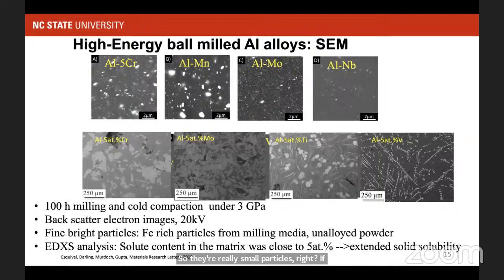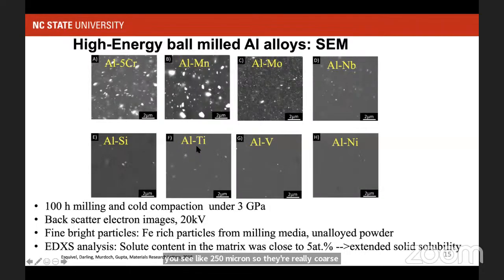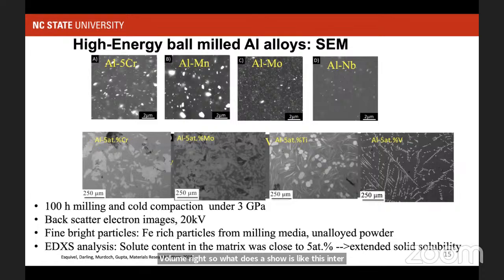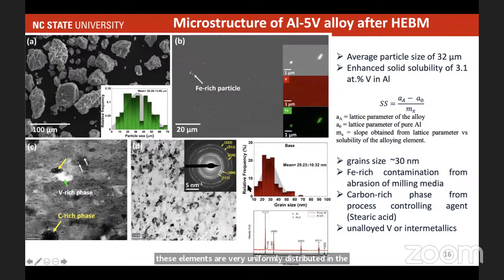If I compare them with the same alloys made by casting, a different route, the microstructure looks something like this, and you see 250 micron, so they're really coarse intermetallics. And if I don't have that, you see those alloying elements are uniformly distributed. If I do EDX analysis here, composition analysis in a volume of around 5 micron in diameter, you see all of these alloying elements are in solid solution within that 5 micron volume. So that shows these elements are very uniformly distributed in the matrix. We further did some TEM and XRD analysis, which confirms this. This just shows you how the material looks.